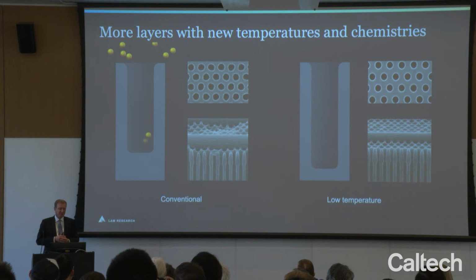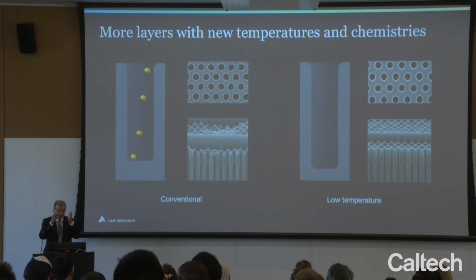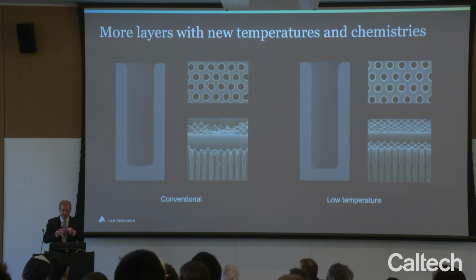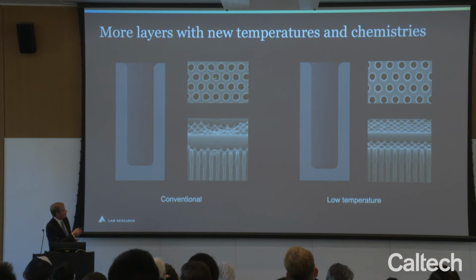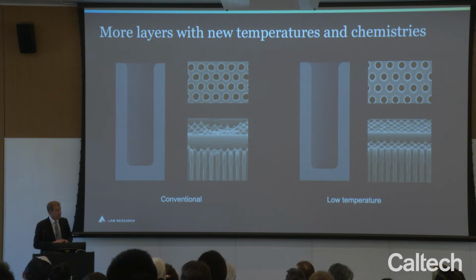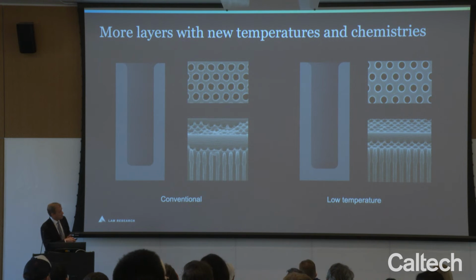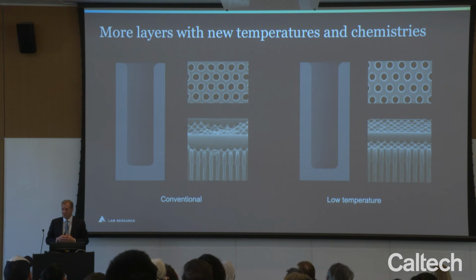We're looking at new process regimes like cryogenic etching. And again, we think about what we can do as we're opening these very small holes. At conventional temperatures where we've typically been operating, the ions are bombarding the feature. There's plasma-generated polymers on the side of the feature, and we end up with some of the holes looking a little bit rough, and roughness is bad because it basically starts to make these holes a little too close to each other, and you end up with problems with the device itself. By going into a lower temperature regime, we're able to control in a much better fashion the neutrals that end up on the sidewall of the etch. We're able to accelerate etch rates, and also, as you can see from the pictures, end up with much better formed features.